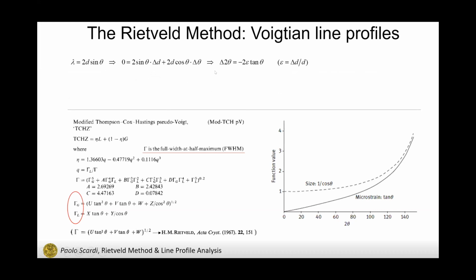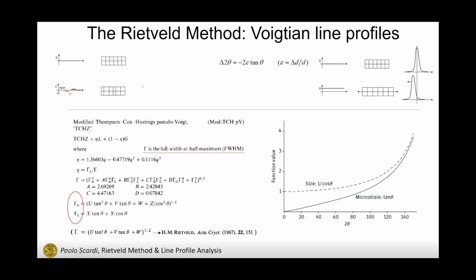If you just differentiate the Bragg law for constant wavelength, you can obtain the effect of a uniform strain that we know very well is just shifting the peak position. And by similar argument, in a sort of heuristic way, you can consider the case of a variable strain, whether of the second or third type, if it is within the grains or from grain to grain.